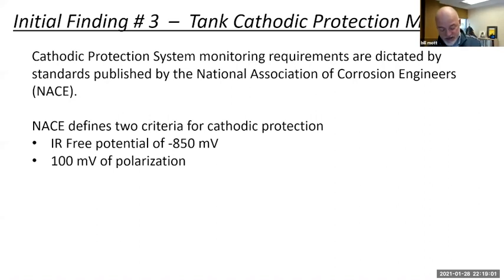One of the findings he passed on was that the instant off readings that were more negative than 1350, and he was giving a little bit more leeway than NACE, were just kinetically not probable. It couldn't happen. He also stated that readings that appeared to be good, that were associated with high readings, also had some of that inherent error in it. So if one reading is bad, it probably indicates that multiple readings have an interference, have an issue.